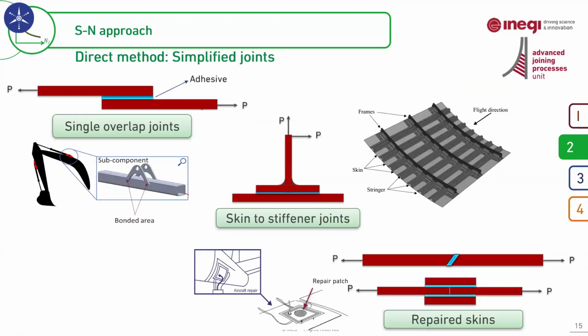The direct method can be simplified even more by testing a representative bonded joint specimen instead of a real subcomponent. For example, instead of testing the full boom connection, we can test a single lap joint, because here it's a single overlap joint. Or for skin to stiffener tests as part of a fuselage, for example, we can do the test on T-joints with the same substrate materials and adhesive.